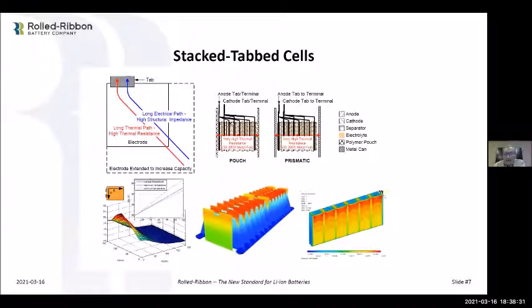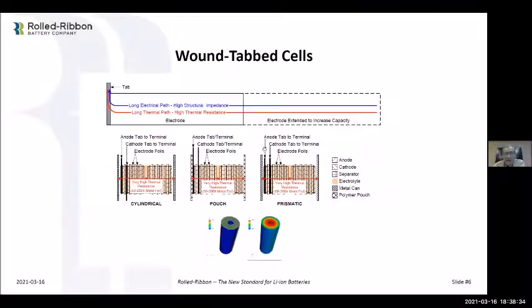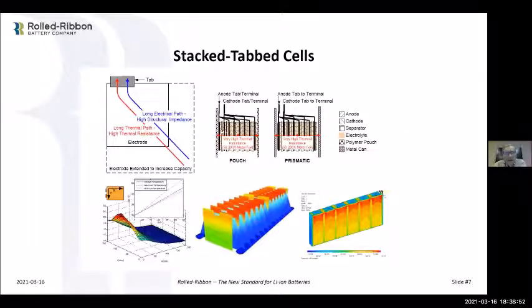If you look at the structure of the cell, it's the same in wound as you saw before. When you wind it up here, the heat has to travel around this coil to get out. It's a welded tab over here. There's a lot of thermal resistance between the wound layers here. Well, the same is true here. When I stack it, I have a lot of thermal resistance, and so the heat still has to get out the welded tabs here, and so you add to it. Same principle applies. If I want greater capacity, I have to increase the square inches of electrode area, get more electrochemical material, and when I do that, the surface area gets longer, so I have more thermal resistance, I have more electrical resistance, and so I'm increasing the impedance. And the path, I squared R, all the same thing.